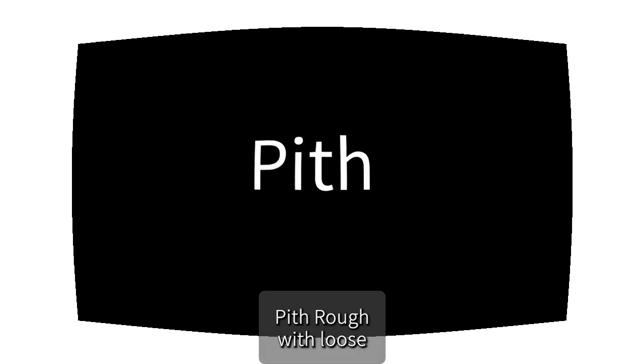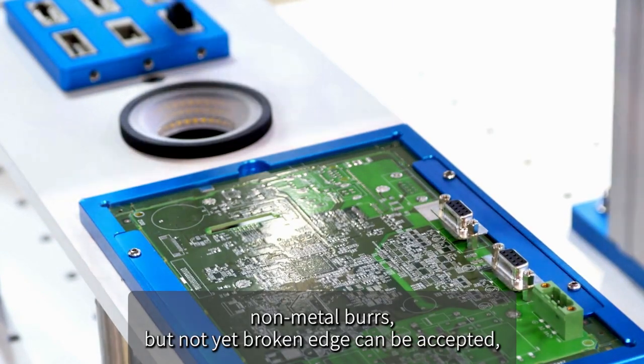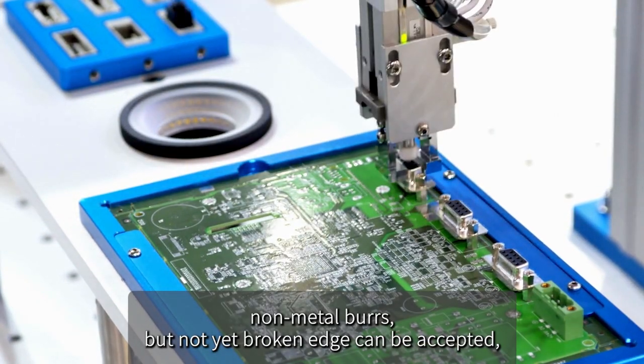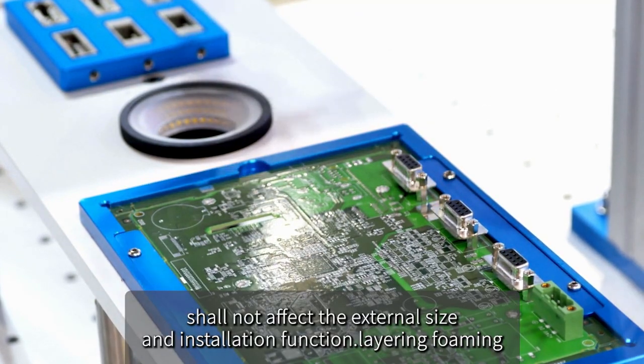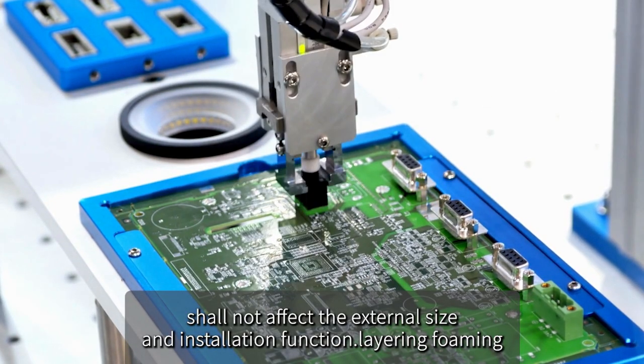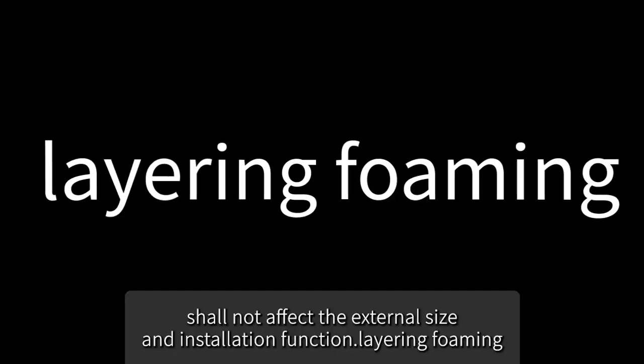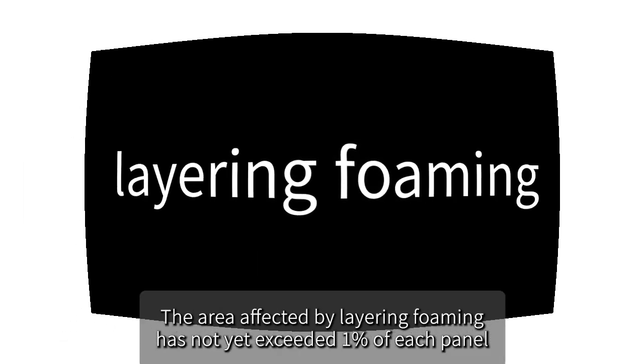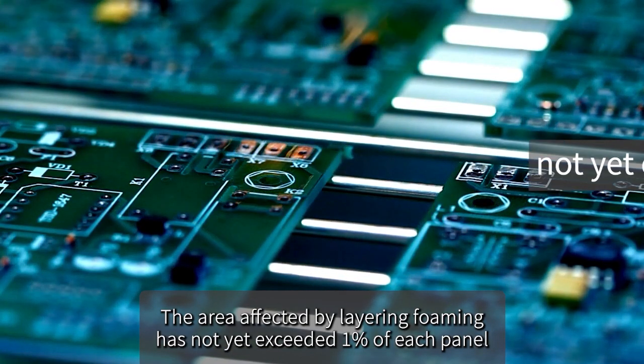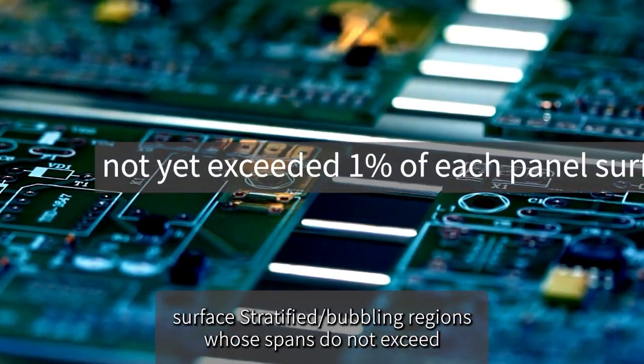Pith. Rough, with loose nonmetal burrs, but not yet broken edge can be accepted, shall not affect the external size and installation function. Layering foaming. The area affected by layering foaming has not yet exceeded 1% of each panel surface.